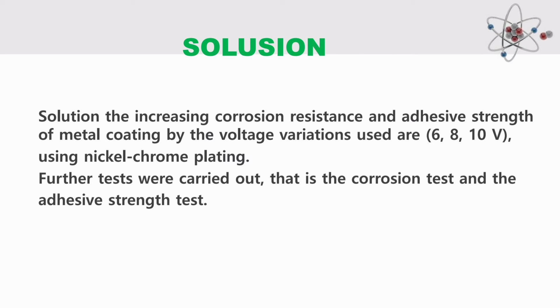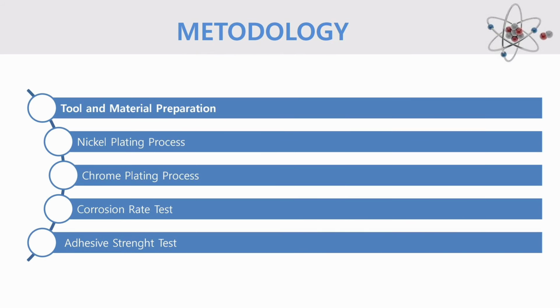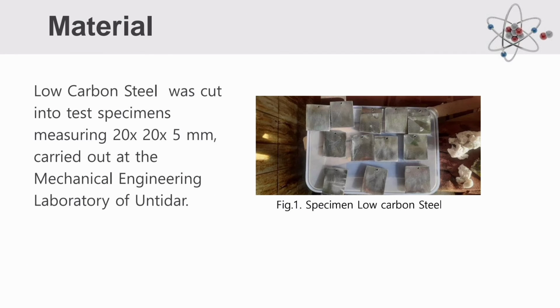Solution: increasing corrosion resistance and adhesive strength of metal coating by the voltage variation used, which are 6, 8, 10 volt, using nickel chrome plating. Further tests were carried out, that is the corrosion test and the adhesive strength test. Methodology: 1. Tool and material preparation. 2. Nickel plating process. 3. Chrome plating process. 4. Corrosion rate test. 5. Adhesive strength test. The material is low carbon steel cut into test specimens measuring 20 by 20 by 5 mm, carried out at the Mechanical Engineering Laboratory of Untidar.